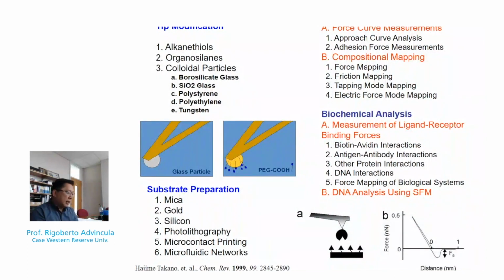The substrate itself can be mica, gold, or silicon wafer. It can be fairly flat, very flat, and quite forgiving. As mentioned, if you couple the force curve measurements, the compositional mapping, one can probe the surface forces, the friction, the non-contact mode, the electrical force, adhesion force, etc.